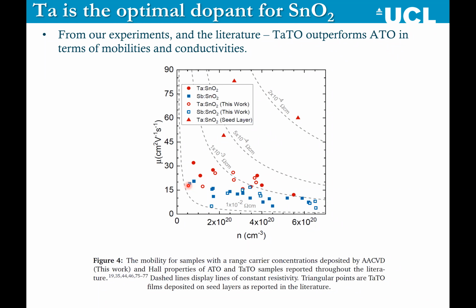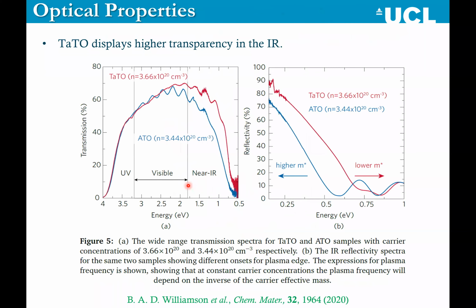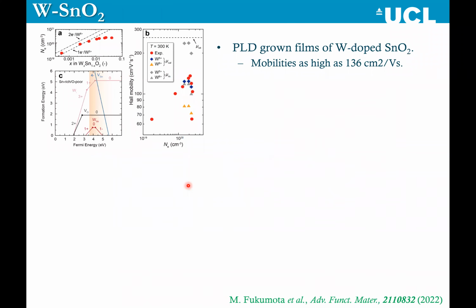And again, these results have been ignored because people couldn't explain them, and they assumed they must have been measurement faults. So again, Tato displays higher transparency in the IR, which can be linked to the plasma energy. So we have the exact same doping mechanism at play here. And again, this helps to bring tin dioxide to higher mobilities and to higher transparencies, meaning that we can use it for more and more devices.